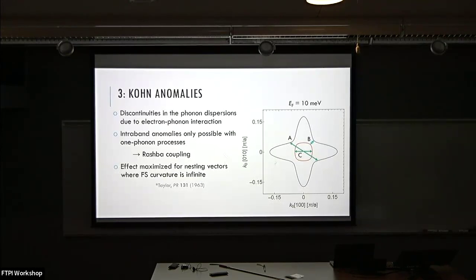Okay, so now the final thing are Kohn anomalies. And if you look at the Fermi surface, you can imagine various connecting vectors where you could expect a Kohn anomaly in the phonon spectrum. And now what the theorists tell me is that for intraband anomalies, they're only possible with a one phonon process. So if there's a question between one phonon and two phonon, you can only get these intraband anomalies with a one phonon.